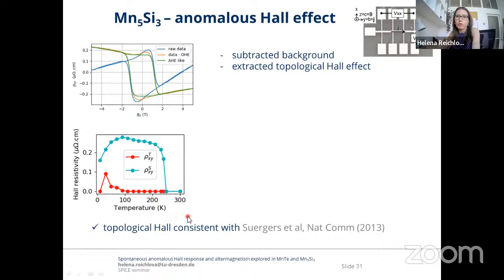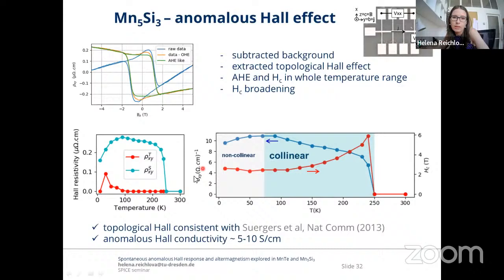When converted into Hall conductivity, we can see that indeed it does not show very clear variation at the magnetic phase transition between the low temperature magnetic and the high temperature magnetic phase. And interestingly, the coercive field is also not changed at all at this phase transition between two magnetic orderings. And both of them are absent in the paramagnetic phase. The amplitude of the anomalous Hall conductivity is between 5 to 10 Siemens per centimeter, and I will come to that also later.